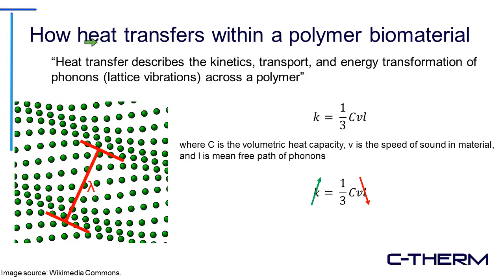Heat transfer within a polymer is described as the kinetic transport of energy through phonons, or lattice vibrations, across a polymer. And it's given by this nice little formula right here, where thermal conductivity is equal to 1/3 times the volumetric heat capacity, the speed of sound in the material, and the mean free path of phonons. So effectively, if we increase the mean free path of phonons, we'll increase our thermal conductivity. Now, how exactly can we do this?